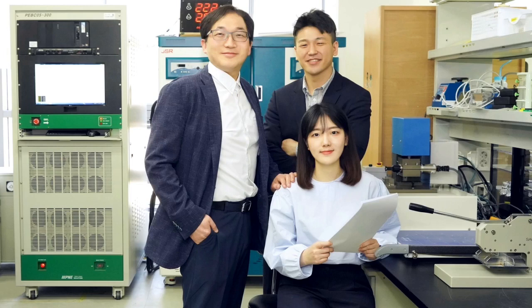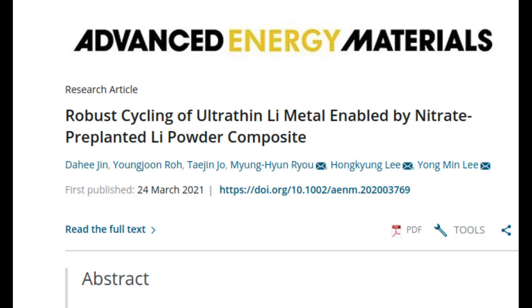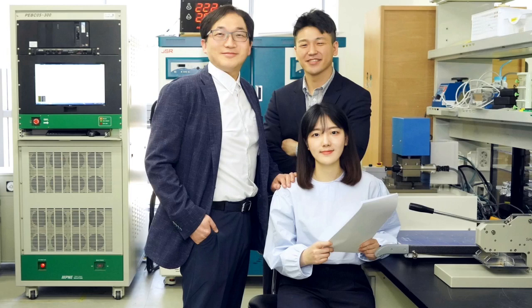The appeal of LMP lies in their spherical shape, which results in higher surface area and ease of thickness tunability, allowing for wider and thinner electrodes. However, problems with LMP use still exist, such as the morphological failure caused by the inherent nature of their uneven surface. Now, in a new study published in the journal Advanced Energy Materials, researchers from Korea adopted a novel approach in which they pre-planted lithium nitrate to the LMP itself during the electrode fabrication process, allowing them to fabricate approximately 150 mm wide and 20 micrometer thick electrodes, which showed a Coulombic efficiency of 96%.